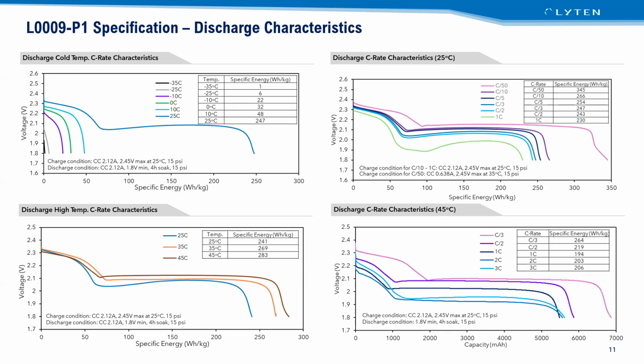Lithium sulfur is weird. This is the other thing that's weird about it. It has this two plateau. So this is a plateau where you're dissolving sulfur here, and then here you're precipitating a salt, an Li2S salt, largely, right? And then you get to a point where there's no capacity left, so that's when the voltage drops off, right?